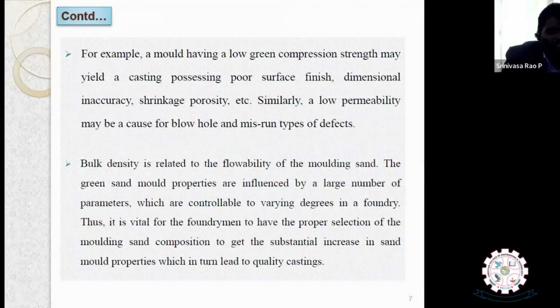If you have a low green compression strength, that yields a casting with poor surface finish, poor dimensional accuracy, and it will also create porosity. Similarly, low permeability may be a cause for blowholes and misrun type of defects. Misrun is nothing but a fluidity problem. The ability of the metal to flow will be decreased. If the ability to flow is decreased, then there will not be a complete casting. There will be some defect, and that defect is known as a misrun defect, or we can call it a fluidity defect.